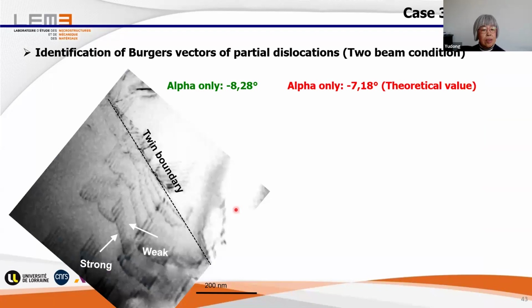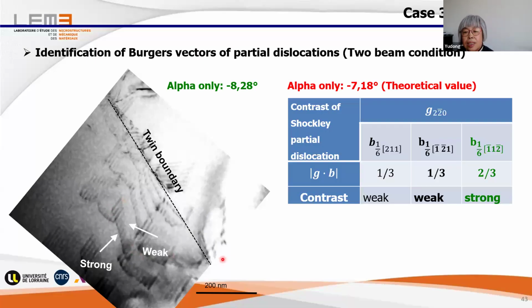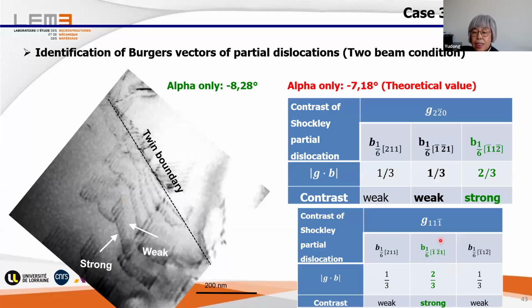And so now we continued and we see the image contrast is not very nice, but we see convincingly clear. For the trailing one, we have a higher contrast. For the leading one, we have weak contrast. And you see, that means the trailing one is this Burgers vector. And added to the first results, we unambiguously determined the two Burgers vectors, this and that.